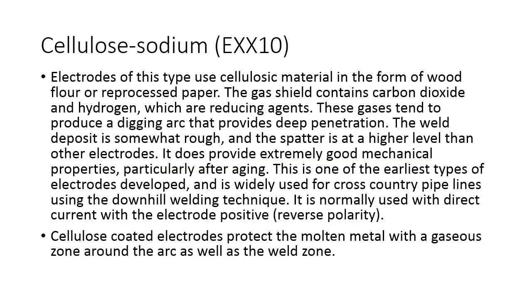Cellulose sodium. Electrodes of this type use cellulosic material in the form of wood, flour, or reprocessed paper. The gas shield contains carbon dioxide and hydrogen, which are reducing agents. These gases tend to produce a digging arc that provides deep penetration. The weld deposit is somewhat rough, and the spatter is at a higher level than other electrodes. It does provide extremely good mechanical properties, particularly after aging. This is one of the earliest types of electrodes developed and is widely used for cross-country pipelines using the downhill welding technique. It is normally used with direct current with the electrode positive, reverse polarity.